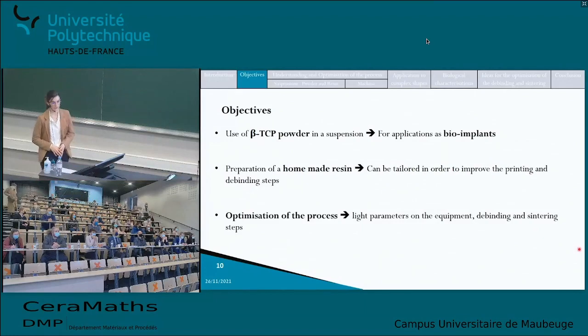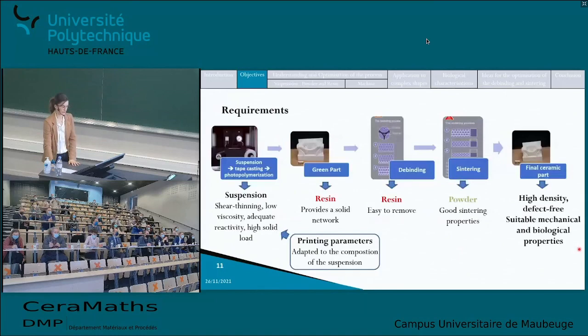The debinding and the sintering step had to be adapted. So there are a lot of requirements that go with this process. First, the suspension has to have a shear thinning behavior with a low viscosity, an adequate reactivity, and a high solid load. And as I mentioned, the printing parameters have to be adapted to the composition of the suspension.